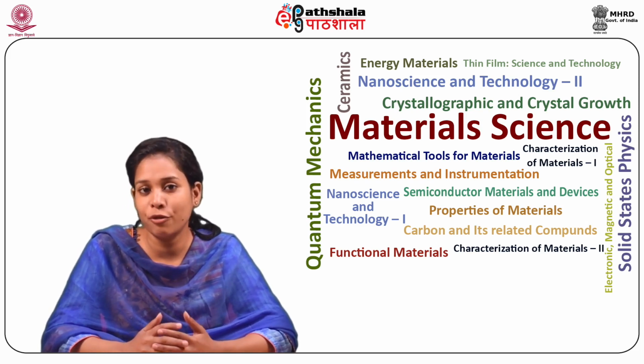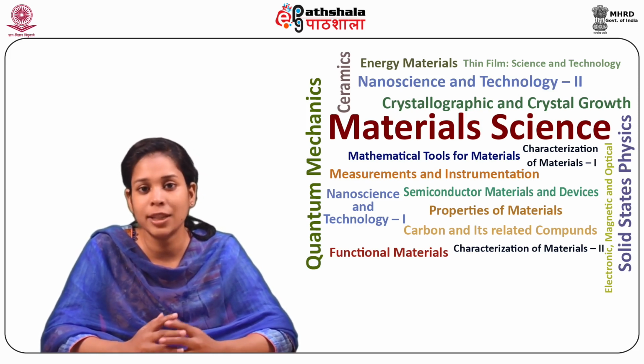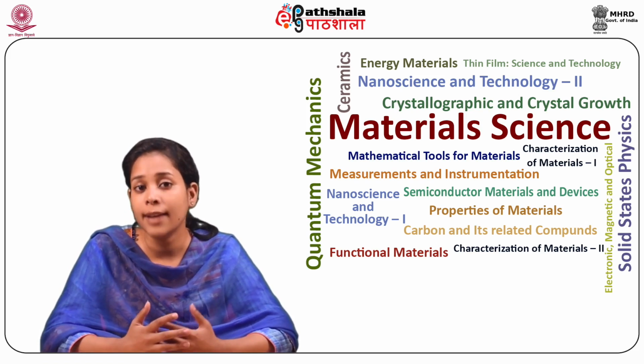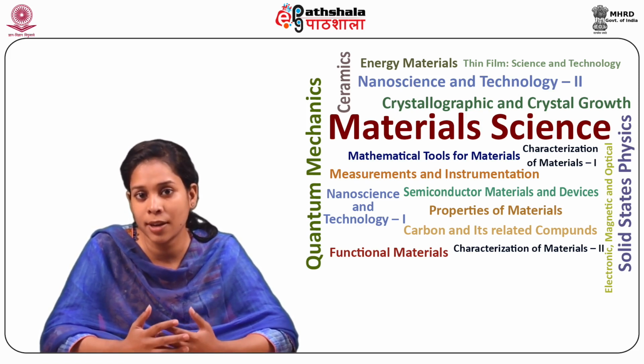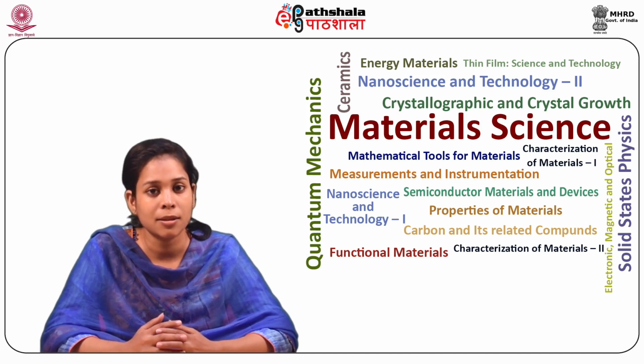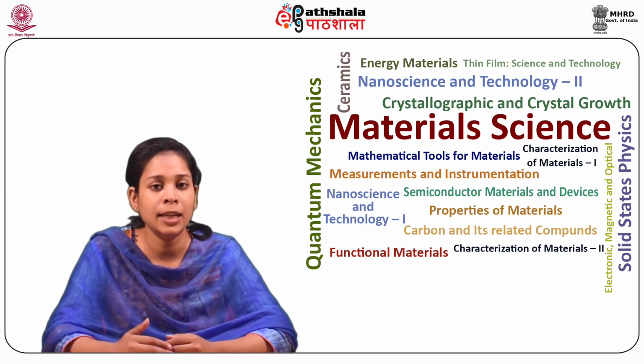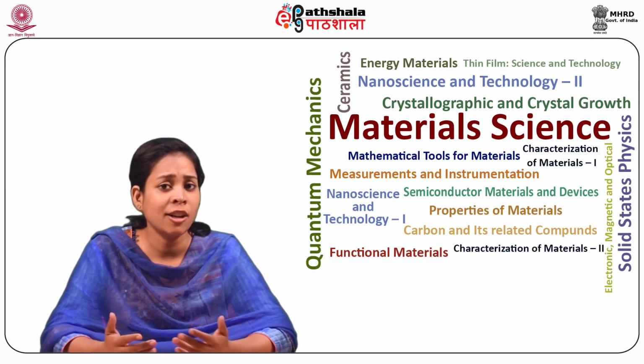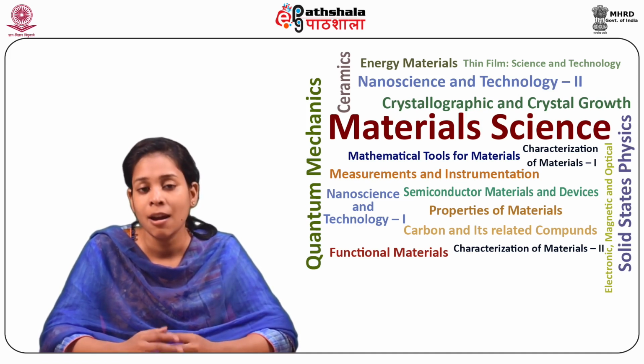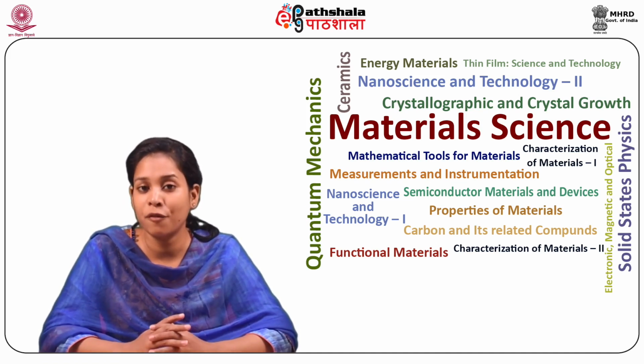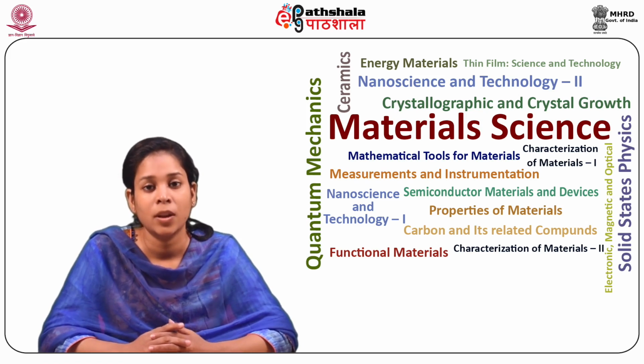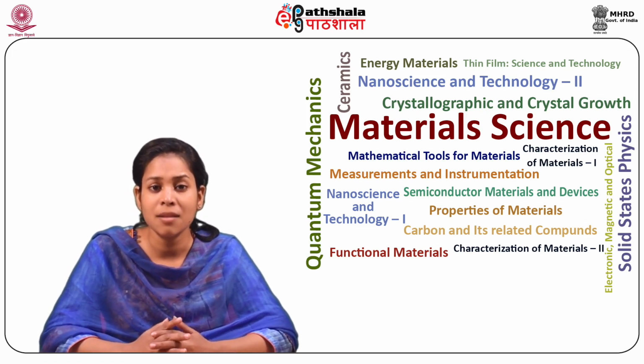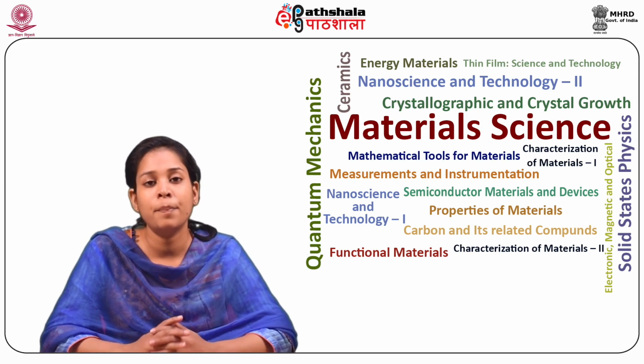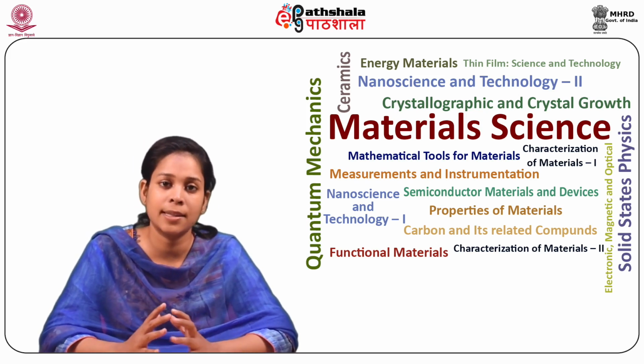A purely covalent bonding therefore cannot produce a random network structure characteristic of glass. On the other hand, ionic bonds are not directional and are incapable of forming a network. So the bonding in a glass must therefore be of mixed character.